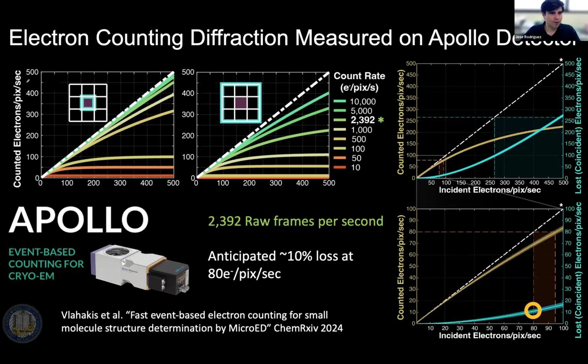And if you go to very, very high frame rates or very, very high counting rates, then you're able to approximate the perfect counting rates. But in most of these cases, you're really only doing well at counting when you have very, very few electrons incident on any given pixel in your detector. Otherwise, you end up undercounting or miscounting. And what we found, at least for this detector, is that with a fluence, or a total number of electrons per pixel per second, that's less than about 80, you could get reasonable counting with no more than about 10% loss, or 10 to 20% loss in counting.